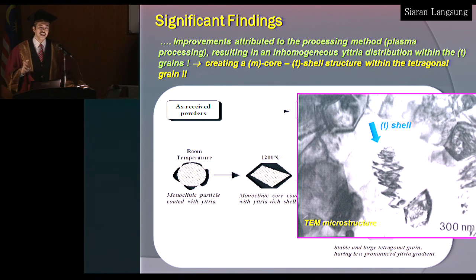Now, this creates a metastable structure because the boundary between the tetragonal shell and the core has a reducing concentration of yttrium oxide. Okay, I did not show the detail here, otherwise I'll be going into too technical. But what we found is that there is a high concentration of yttria at the boundary and very low concentration of yttria at the center of the grain. So that creates a metastable grain, which will respond immediately to propagating cracks. And that enhances the toughness.